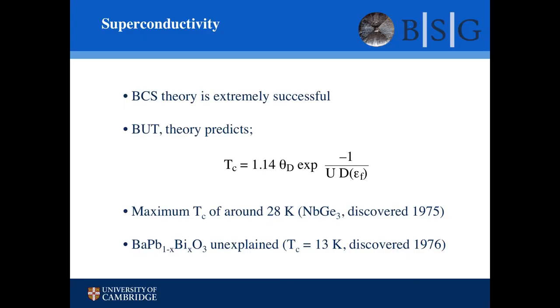So here's a thing, especially for young people in the audience. This theory is called BCS theory. Bardeen, Cooper, Schrieffer all won the Nobel Prize for this, and it makes a very definite prediction. The best theories make experimentally validatable predictions, and this predicts the TC, and there are three variables here. Theta D is the Debye frequency, the frequency with which the lattice can move, understandable. U is the energy gain, or energy loss, that the superconductors can undergo by moving into the superconducting state. D epsilon F is the density of states. These electrons have to condense into available energy states.